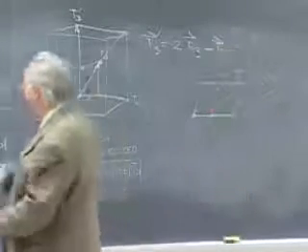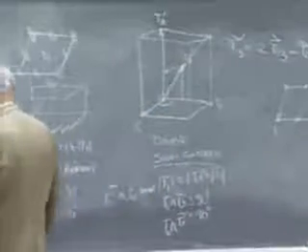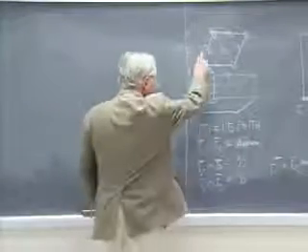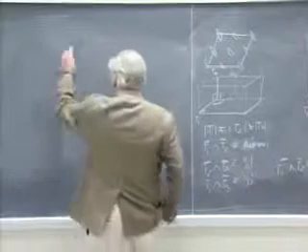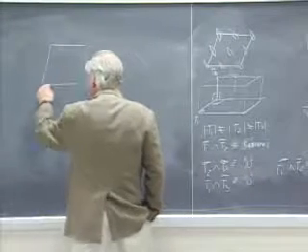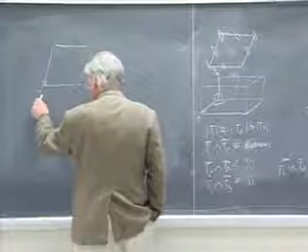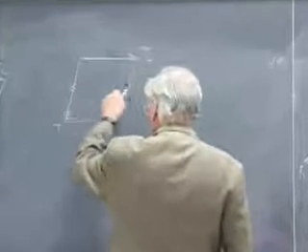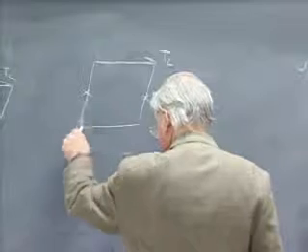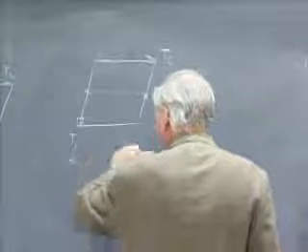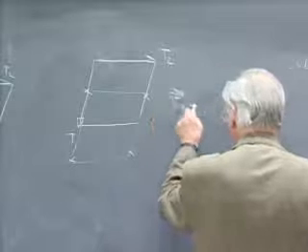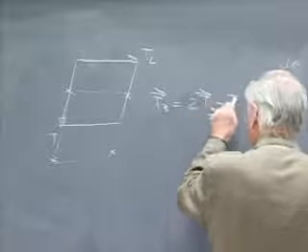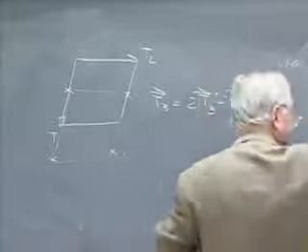Okay, well, in P2 there are four different kinds of twofold axes. So we could have the third translation terminate over either of the remaining pair of twofold axes as well. I think that it's apparent that if I pick T3, the original T3, as 1/2 of T1, so that the next layer up terminates in lattice points in this orientation, and then I pick a T3 prime, which is equal to 2T3 minus T1, I will have gotten, again, a side-centered lattice.